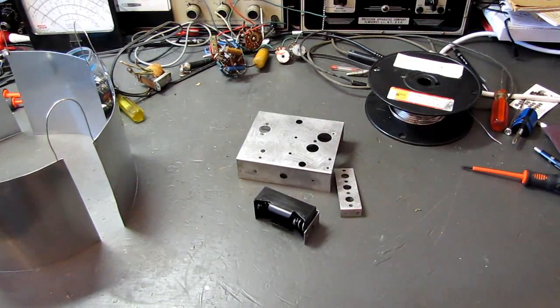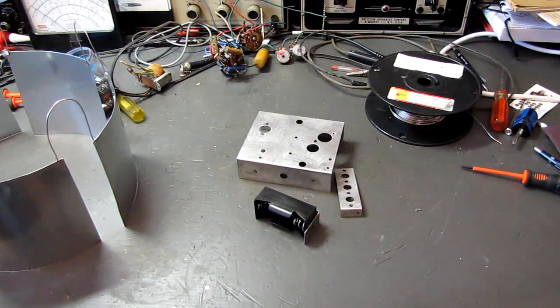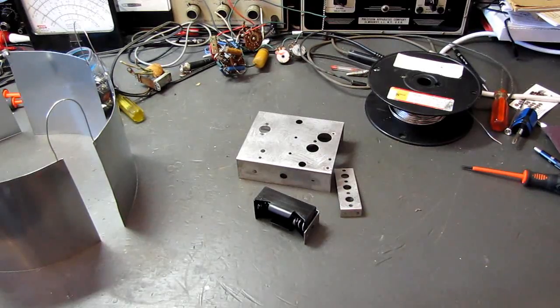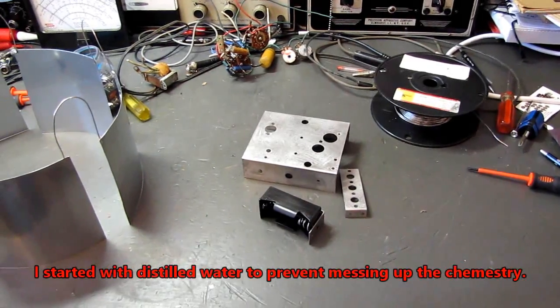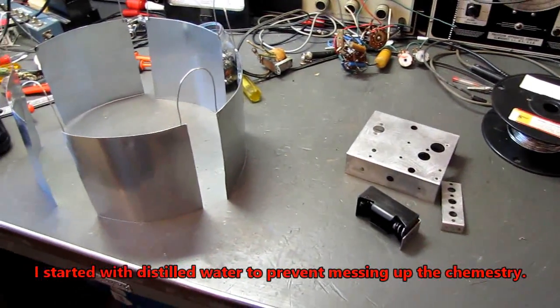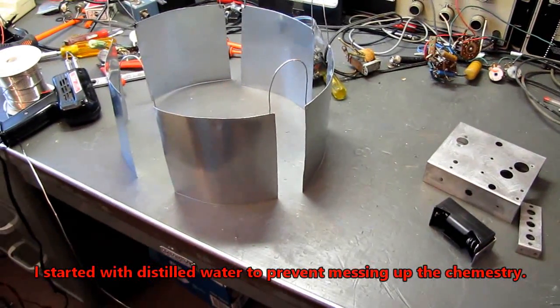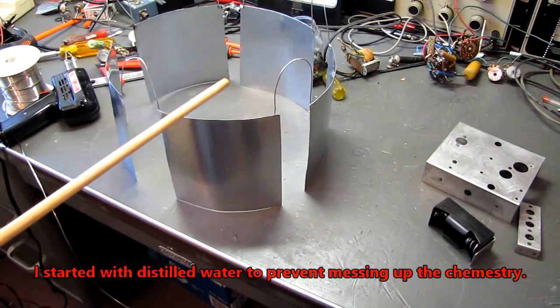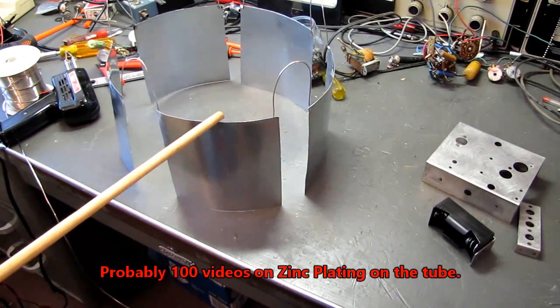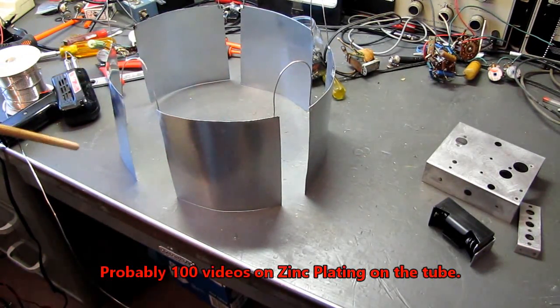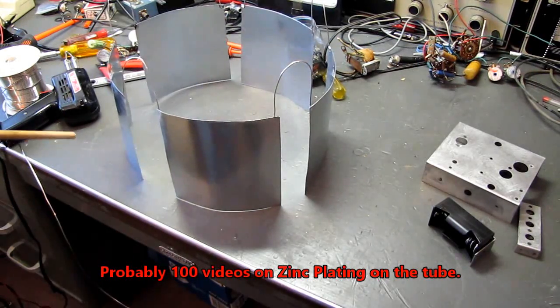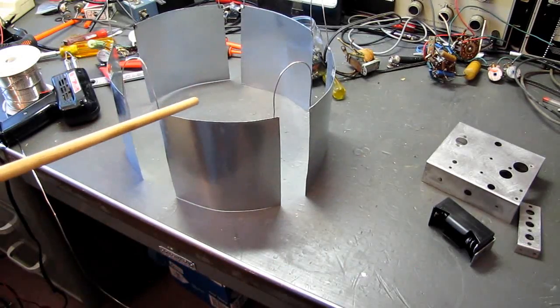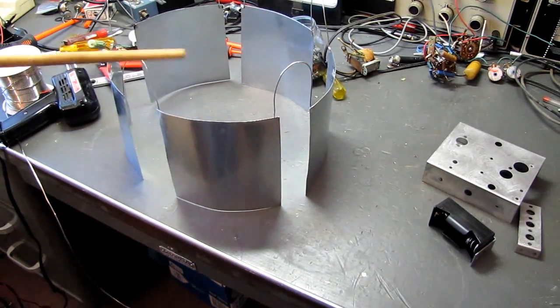Now I've had a two pound block of zinc sitting in the acidic bath here for almost three days. And the water's turned a nice charcoal color. So there should be plenty of zinc in the fluid to start the plating process. But I've also purchased some sheets of zinc, pure zinc. These are very thin, 0.24 millimeter or 10 thousandths of an inch thick sheets.